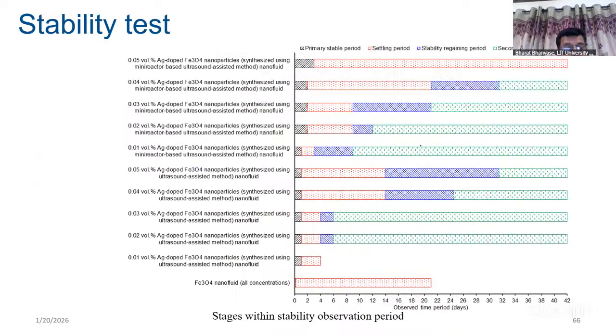Stability study was carried out at different volume percentages: 0.01, 0.02, 0.03, 0.04, 0.05. One phenomenon observed is the primary stable period. After that, settling is observed. Then comes the stability regaining period, where some cluster formation takes place that improves stability again, meaning the interactive forces between nanoparticles get balanced, leading to complete stability. This is called the secondary stable period.